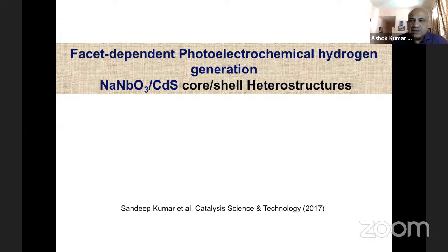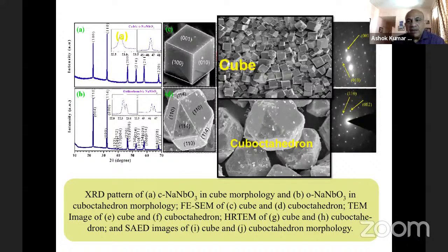Now, this is one more system where we have tried to design such that you have higher efficiency. And this uses the morphology of the nanocrystals. So it is a core shell structure of sodium niobate and cadmium sulfide. And the sodium niobate is the core and cadmium sulfide is the shell. But this core material itself we can make in different shapes.